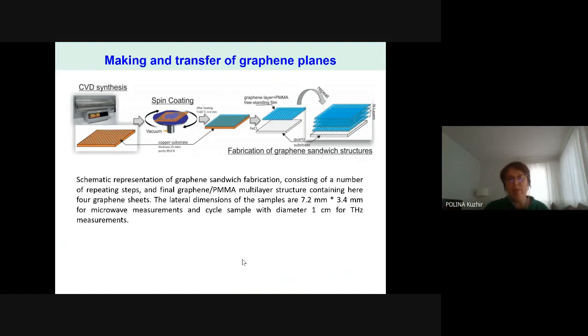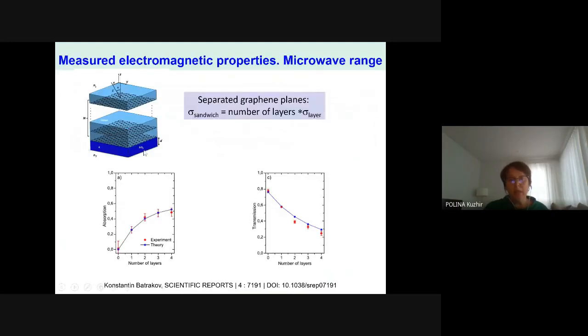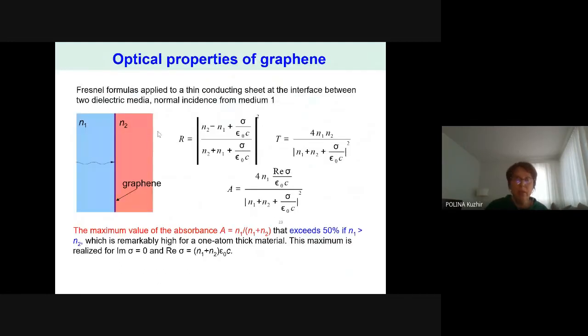So if you compare it with a not-very-lossy material whose thickness is less than 100 nanometers, you could forget about that effect. Moreover, this thin layer of polymer allows us to decouple the graphene layers from each other, and we could treat the conductivity of the overall sandwich structure as the conductivity of one graphene layer multiplied by the number of layers. What's also important, of course, if we speak about freestanding graphene or 2 graphene layers, is that it is incredibly absorptive—it could absorb, at proper conductivity, up to 50% of electromagnetic radiation.